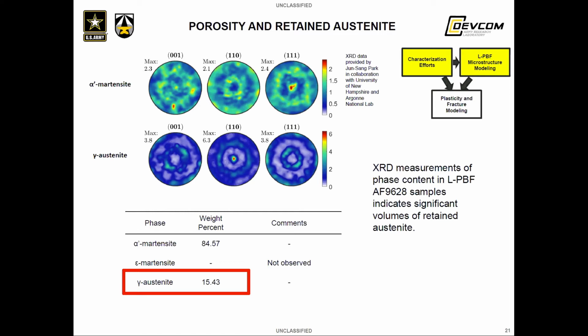The phase content of AF9628 is another quantity that can be controlled by a manufacturing process. As the transformation of retained austenite has an effect on the final material's properties, this is also an avenue through which we can control mechanical properties with processing parameters. Current efforts to model the formation of retained austenite will serve to map out the space of austenite content as a function of powder bed fusion parameters.